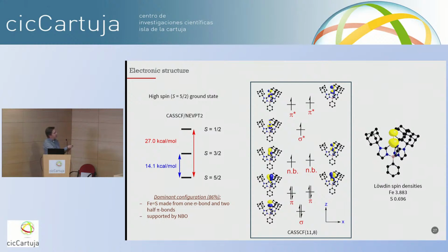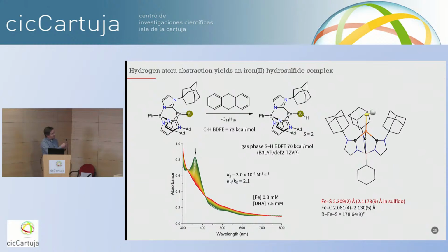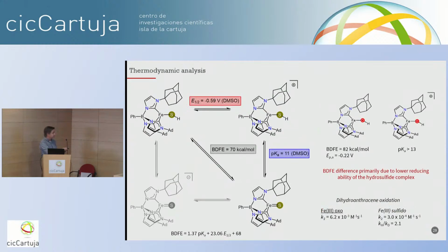And so I think the ligand for sure helps to stabilize this, despite the fact we've actually quenched one of the metal-ligand multiple bonds. This compound is still reactive, so we can also react it with dihydroanthracene to make the hydrosulfide complex. This is a nice clean reaction. We can compute the SH bond energy of around 70 kcal per mole. It's very much like an organic hydrosulfide.